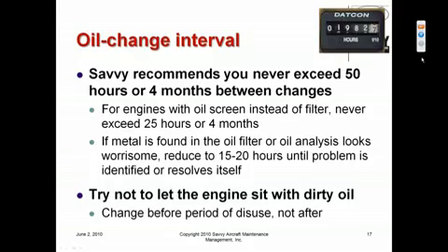We recommend never exceeding 50 hours of operation or 4 calendar months, whichever comes first. The reason for the 4 calendar months is that as oil gets more and more time on it, there tends to be more and more buildup of corrosive material, particularly acids in the oil. The oil has acid neutralizers to combat this. That's one of the additives that all aircraft operating oils have.